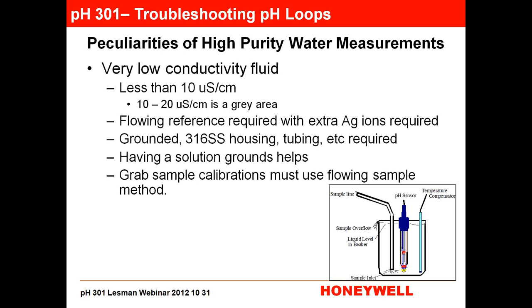what's called a flowing sample. And that flowing sample is really easy to do. You have to have a sample line that is flowing out of your pure water device, and usually they're already set up with samples flowing out into a big sink. And then you take that sample tube and put it at the bottom of the beaker, and you put your pH sensor, and if you have a separate temperature compensator, you pop that in. You put your portable pH sensor in there, and everything is at the bottom of the beaker, and you let it overflow, at least turn over about 3 times.